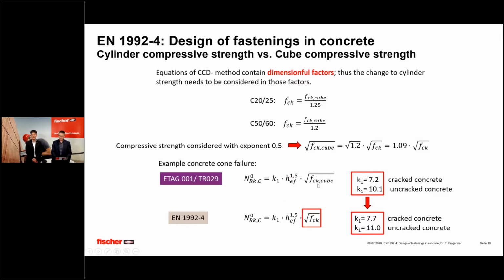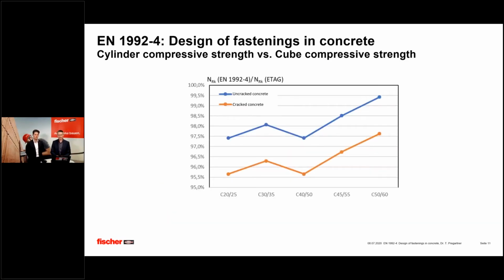It changed the reference from cube strength to cylinder strength, and the factors also changed slightly, which means they got increased from 7.2 to 7.7 in cracked concrete and 10.1 to 11 in uncracked concrete. In general, you have to consider that even if you consider the cylinder strength already with the dimensional factor, you still have to insert the compressive strength under the square root, and that causes the fact that considering both the dimensional factor, which got increased,